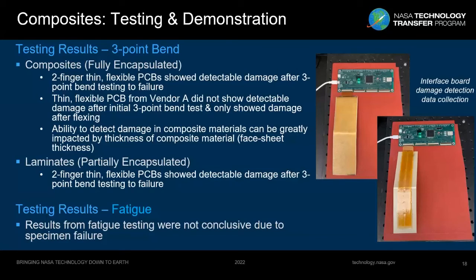The fatigue testing, unfortunately, didn't provide quite as conclusive results where we were just flexing it. The problem we ran into is that we were flexing and not seeing much damage, and we continued to increase the load. And then, lo and behold, the systems actually failed, and we didn't really get a lot of good data. We are trying to develop a process to do this data acquisition in real time to see if we could see the damage while the flexing was occurring, but we did not have time to complete that due to some funding constraints. Next slide.